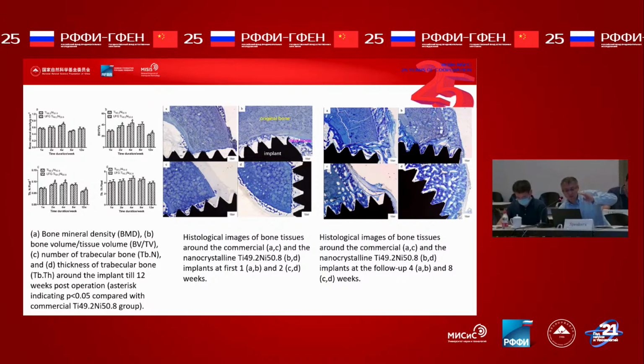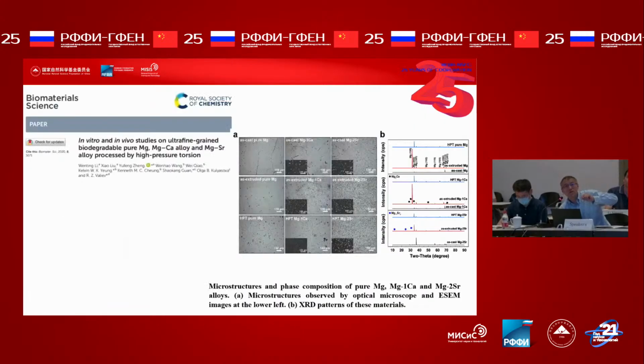You can also find that after implantation into the bone, it has a better new bone forming ability in comparison to the commercial microstructured counterpart. Next slide. We also use this technique to fabricate ultrafine grain biodegradable magnesium alloys. In comparison to the previous study, here we use the high pressure torsion technique, and you can find that the grain size has been decreased significantly by this technique. Next slide.